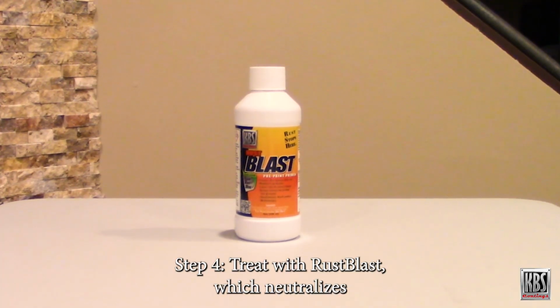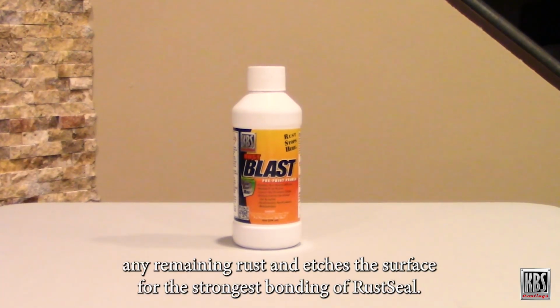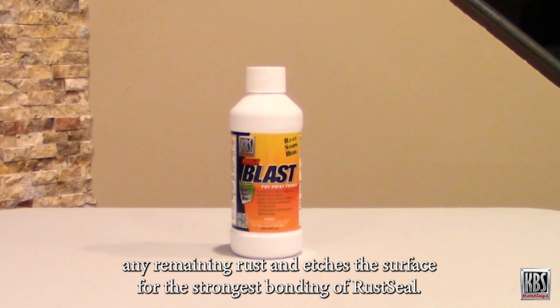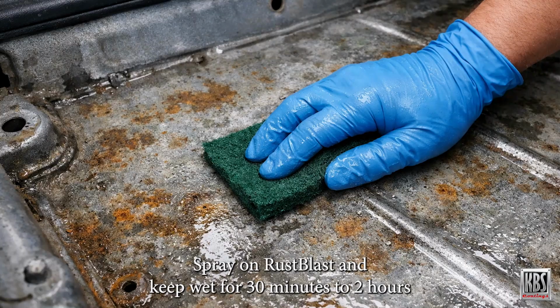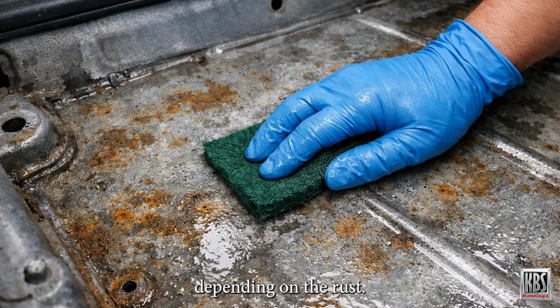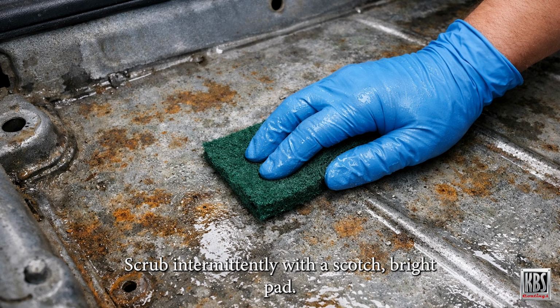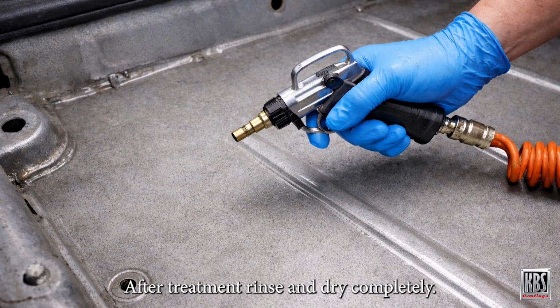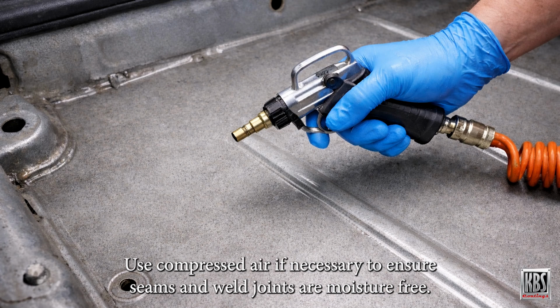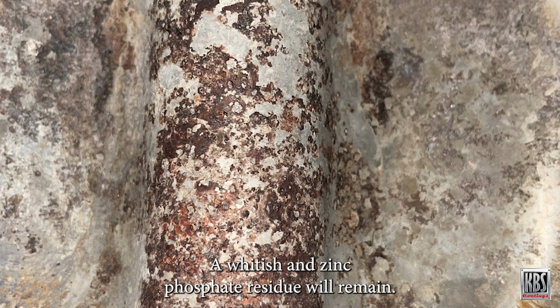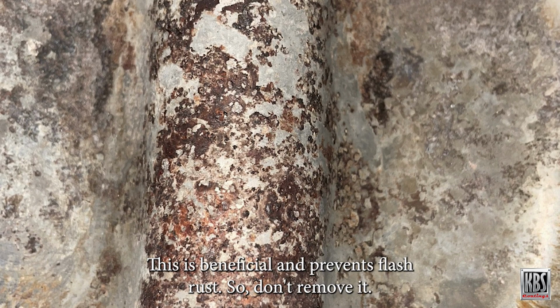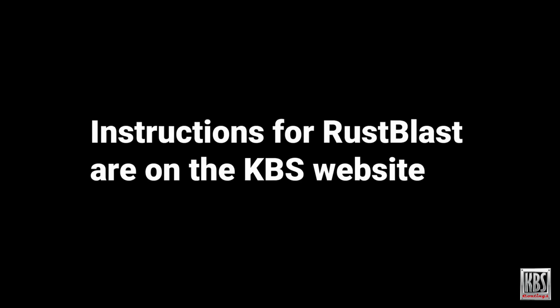Step 4. Treat with Rust Blast, which neutralizes any remaining rust and etches the surface for the strongest bonding of Rust Seal. Spray on Rust Blast and keep wet for 30 minutes to 2 hours depending on the rust. Scrub intermittently with a Scotch-Brite pad. After treatment, rinse and dry completely. Use compressed air if necessary to ensure seams and weld joints are moisture-free. A whitish zinc phosphate residue will remain. This is beneficial and prevents flash rust, so don't remove it. Detailed instructions for Rust Blast can be found on the KBS website.